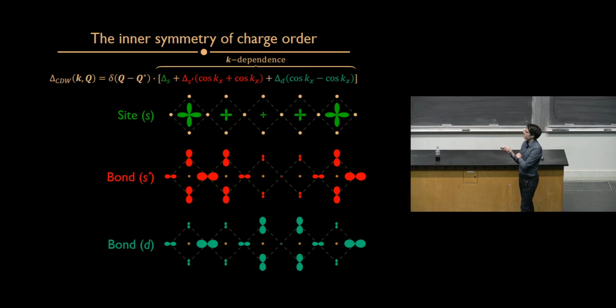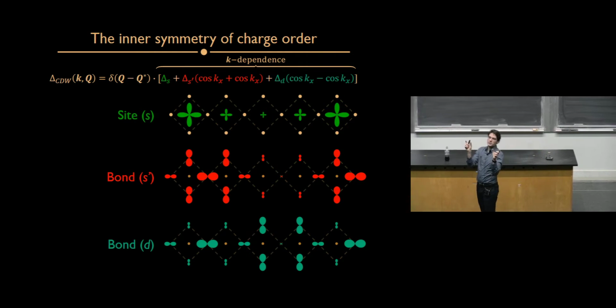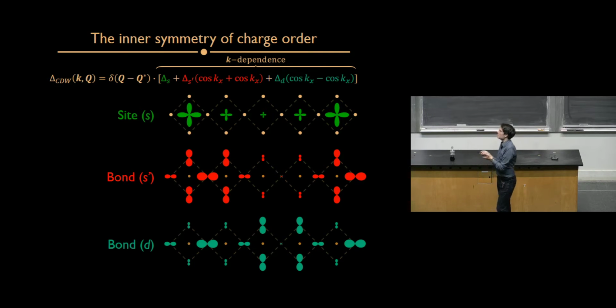And then we can have two different types of bond order. Bond meaning that the charge sits in the bond between the copper, so it sits on the oxygen 2p states. And you can have one where the maximum of the charge on the horizontal oxygen 2p states is in phase with the charge on the oxygen 2py states. So it's maximum here, and then it oscillates, but it's always maximum together, right, or minimum together.